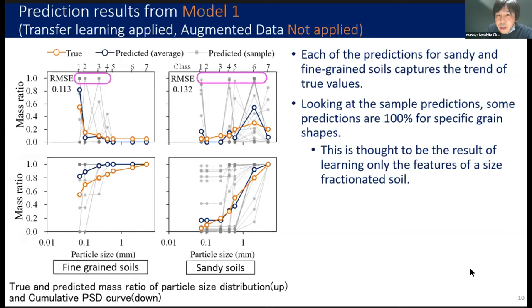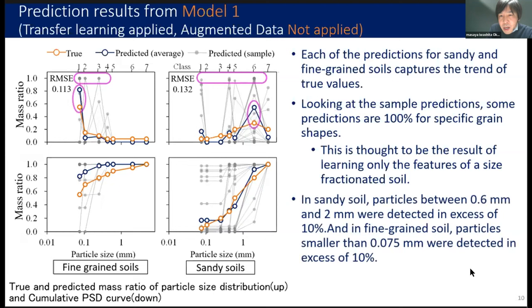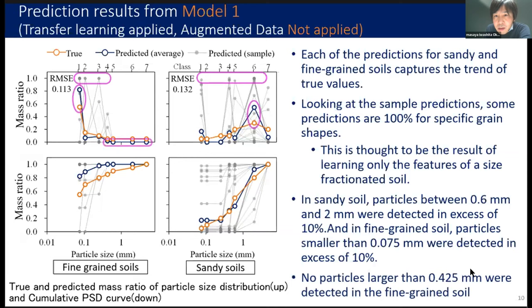In sandy soil, particles between 0.6 millimeter and 2 millimeter were detected in excess of 10%. And in fine-grained soil, particles smaller than 0.075 millimeter were detected in excess of 10%. Note that no particles larger than 0.425 millimeter were detected in the fine-grained soil.